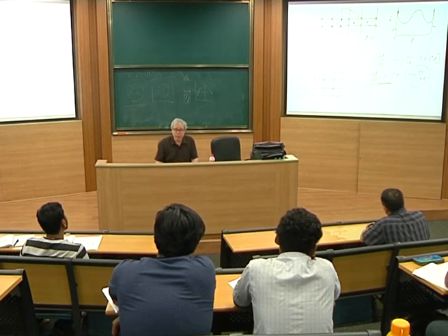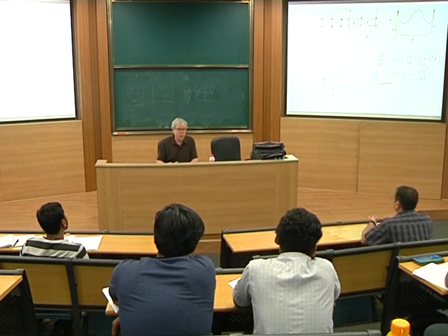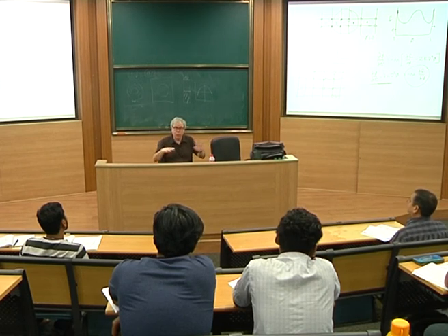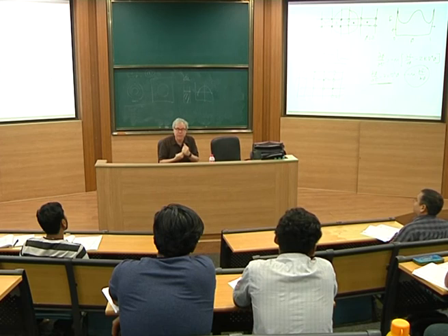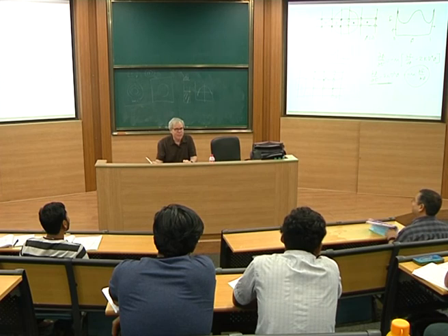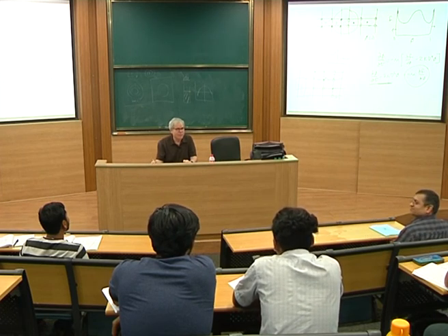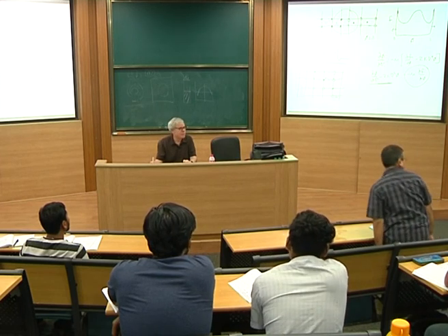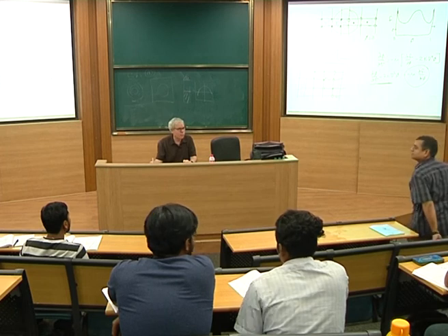When I asked John Cahn about this, his response was that in a crystal, every time you have a composition fluctuation, you generate long-range elastic stresses, and we'll talk about this in a couple days. These long-range elastic stresses give you longer-range interactions, which mean that you should see the linear theory, at least in crystals with systems that have long-range elastic interactions. It's a good PhD thesis for people. Still an unknown question out in the literature. Other questions? You get a chance to prove John Cahn right.